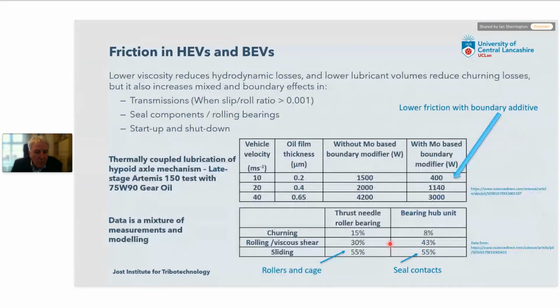Well, for a long time, internal combustion engines have been modeled using hydrodynamic lubrication. My feeling is that this has been done because it's comparatively easy to do. So full fluid film lubrication models are very common. Lubrication models which also incorporate mixed and boundary lubrication, less so. And I think it's tended to push us in the direction of believing that actually mixed and boundary friction isn't particularly important. And I think it is. I think it could be quite a significant oversight that we've made in our modeling of all kinds of mechanisms. There's a couple of examples here. The first one is this axle mechanism. You can see that there are two power loss columns here.